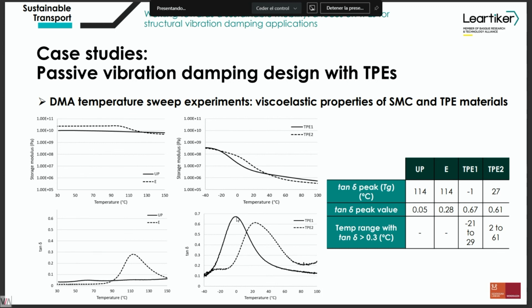In that case, we can see, for example, that the TPE1 material depends on the material selection. This specific TPE has the loss factor peak, which I didn't mention is related with the glass transition temperature. The dissipation capability of the materials is at its maximum at the glass transition. Here the tan delta peak temperature of these materials is at -1. That means that with these materials we would be able to have structures with good vibration damping capability. But of course, this depends on the material selection and the final targets we obtain.